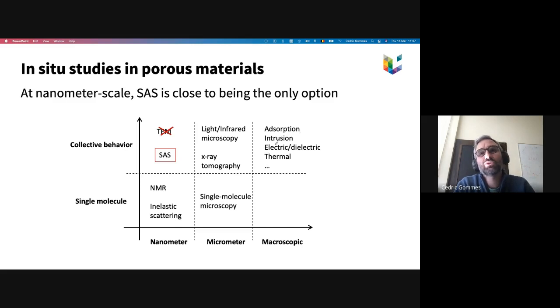And then, if you want to do the same type of experiments with spatial resolution, you could do visible light microscopy down to the micrometer range. But if you start to be interested in nanometer scale phenomena, basically as soon as you're concerned with liquids or putting things inside pores, this rules out electron microscopy. And so there is very little you can do. Small angle scattering is one of the few things that you can do to analyze, typically, phases inside nanopores experimentally.